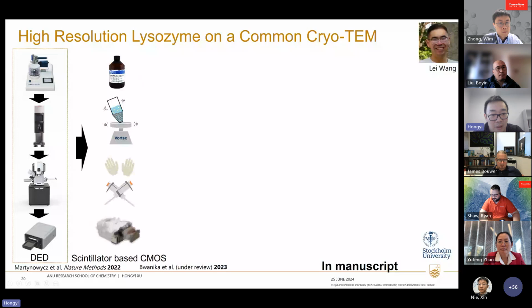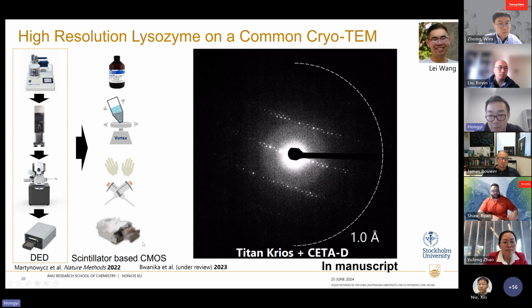So we do the crystallization method by using beads and seeding procedure. So we make a lot of seeds of small lysozyme crystals, and then we're adding a little bit more lysozyme at the end to recover the fragments. And then because there are a lot of seeds, the crystals don't grow very large, and the protein is used up very quickly. And then we do hand blotting, which is a new procedure, and then we use a scintillator-based CMOS detector. So this was what Lei could get.